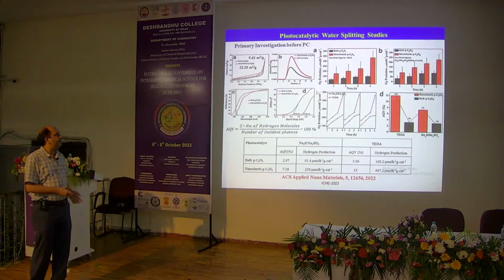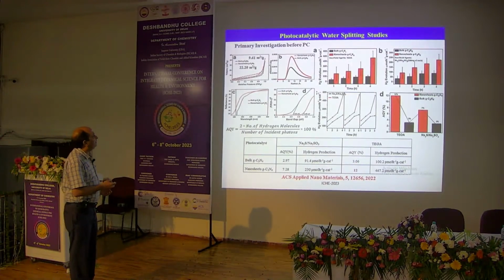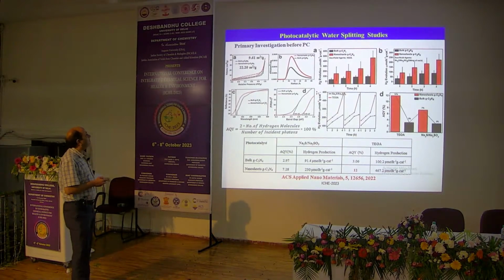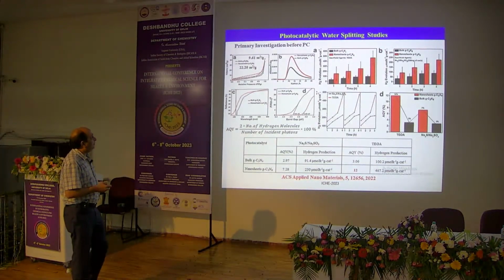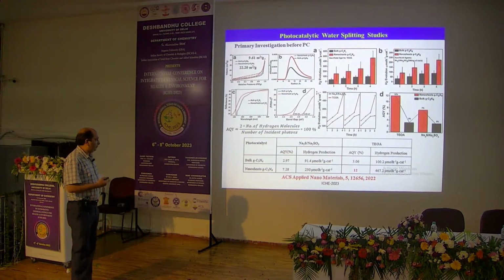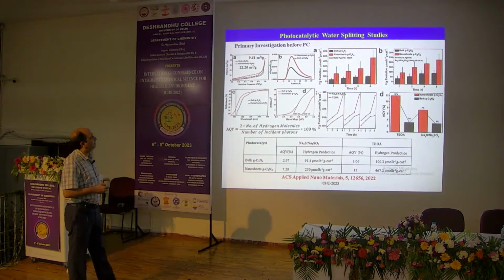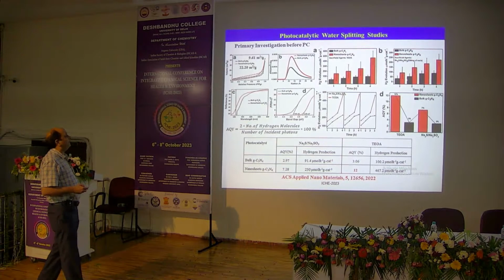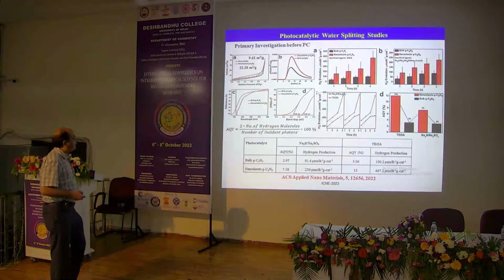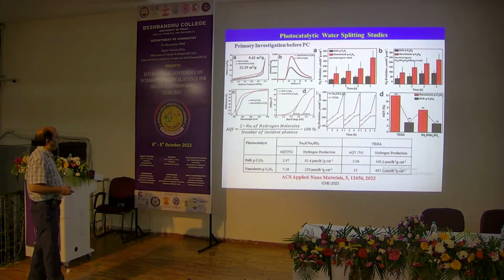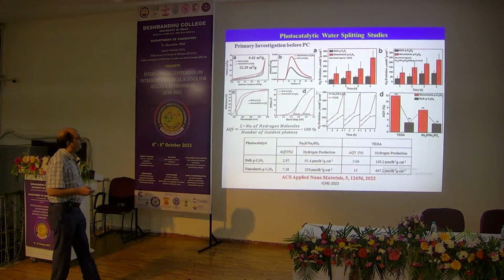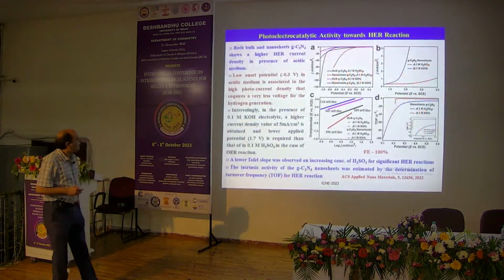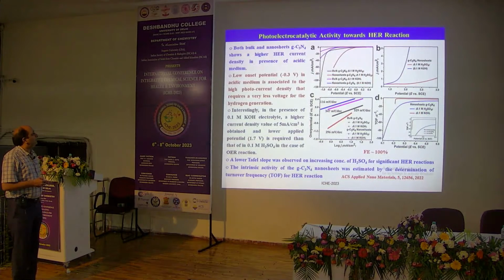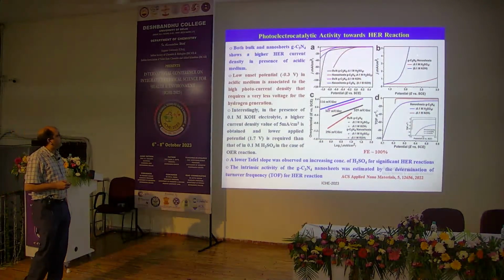We perform the two different sets of reactions simultaneously, and we observe that triethanolamine can generate a high amount of hydrogen, which is around 470 micromole per hour per gram, with an apparent quantum yield of 12%, whereas sodium sulfide and sodium sulfite can generate around 230 micromole per hour hydrogen with an apparent quantum yield of 7%. Then these are the photoelectrochemical activities towards HER reactions.